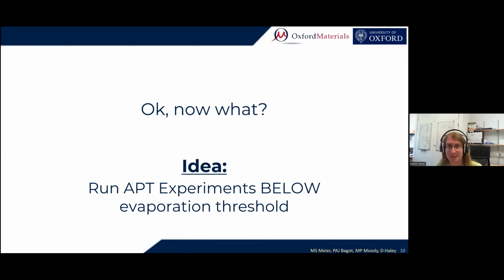We could run APT experiments below the evaporation threshold. And that sounds silly, but it actually makes complete sense. Think about this: contaminant hydrogen is arriving at our tips whilst the experiment is running. And this means even if the electric field is so low that there is no tungsten coming out of our tip, there's still a potential for contaminant hydrogen to arrive at our tip, to evaporate and get detected. And this means up to the evaporation threshold of tungsten, we can very precisely navigate to any electric field and see what the hydrogen spectrum is doing in there.